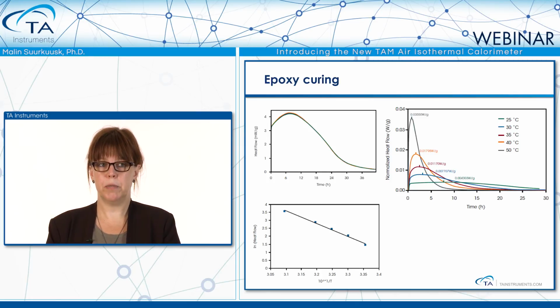And we can see the higher the temperature, the faster the process, and more heat is evolved early in the process. In this case, we have done an Arrhenius relationship, but the top value of the heat flow is taken as the extent of reaction has come to the same point in the process. So we can take the rate of reaction at the peak temperature, a peak maximum, and plot them in a relationship as in the lower left graph here. And we can see that if the logarithm of the heat rates will fall onto this line, we can assume that the process is following the same mechanism.